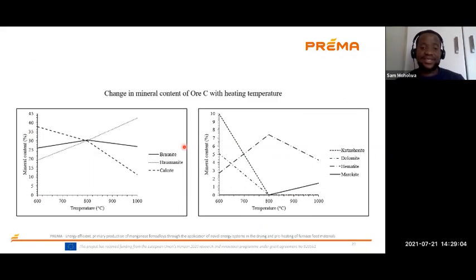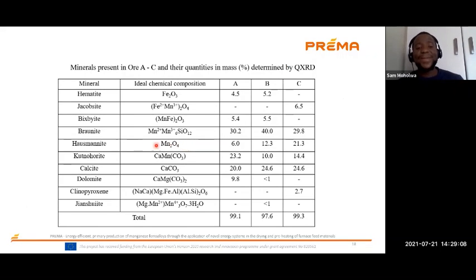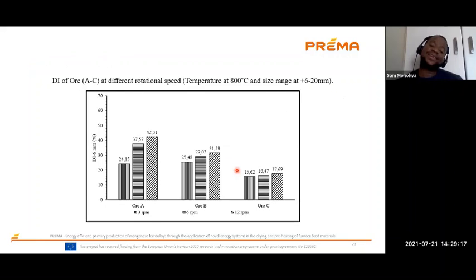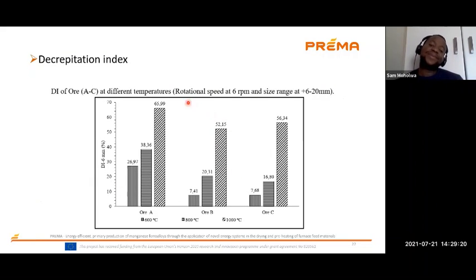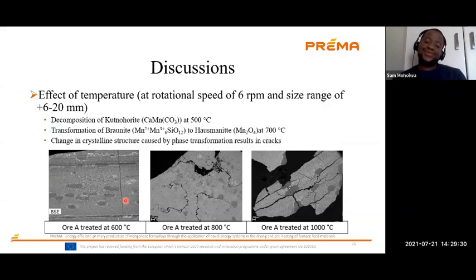And if you remember, if you can just go back to the mineralogy here, OA has the highest content of kutnohorite, which is why here we have OA being the one that is more susceptible to decrepitation because of this kutnohorite content. And as you raise this temperature, the decomposition of this kutnohorite intensifies, which is one of the reasons why the DI increases as you increase the temperature.